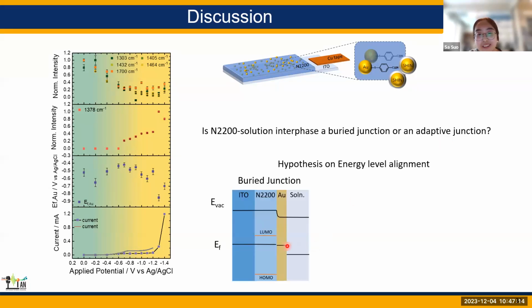And I did some prediction of the energy level alignment in both cases. If N2200 can work as a buried junction, I think this would be what's happening. This solid line represents the Fermi level, and the upper lines represent the vacuum energy. After the N2200 is reduced, there will start to be a potential drop at the gold solution interface. And before that, the potential will drop mainly at the N2200 and gold interface because of the large resistance.